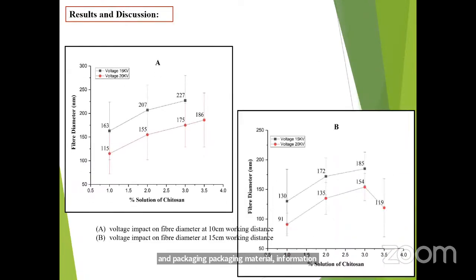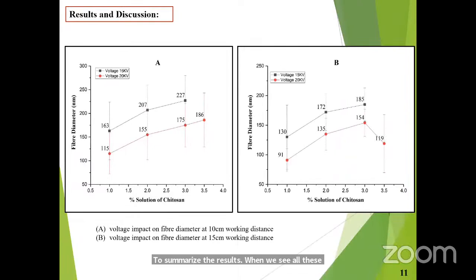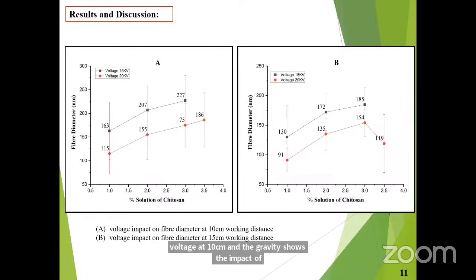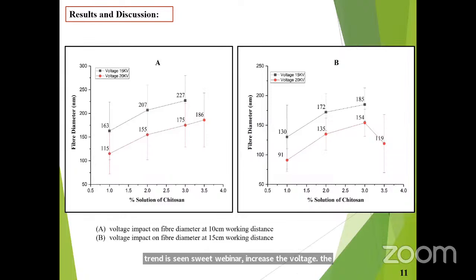To summarize the results, we see all these results in two graphs. Graph A shows the impact of voltage at 10 centimeter and graph B shows the impact of voltage at 15 centimeter. The trend is the same. When we increase the voltage, finer fiber is produced. The red line shows finer fiber produced at 20 kV voltage, and the black line shows that, as compared to 20 kV, coarser fiber diameter was produced by applying 15 kV voltage.